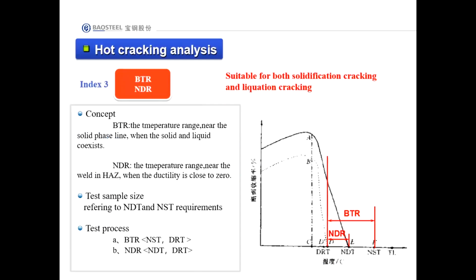The values of BTR and NDR can be further used as the criteria for both forms of hot cracking, that is, solidification cracking and liquation cracking. The BTR is the temperature range near the solidus line where solid and liquid coexist. NDR is the temperature range near the weld in the HAZ where the ductility is close to 0. So this data we often use in our company, in our research.